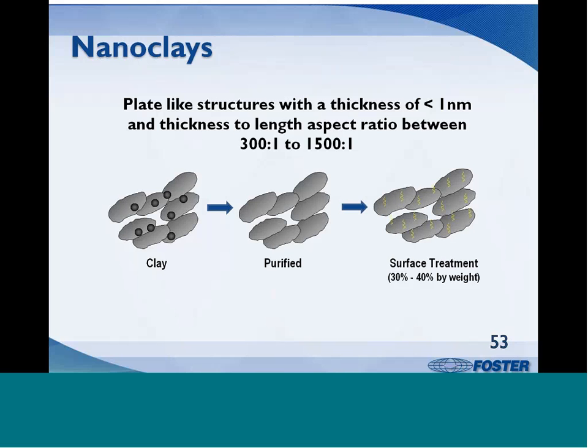It is difficult to quantify the aspect ratio of a plate-like particle. The convention with nanoclays is to ratio the length or width to the thickness. With nanoclays, the thickness is on the order of 1 nanometer, and the width or length is around 300 to 1,000 nanometers, or close to 1 micron.